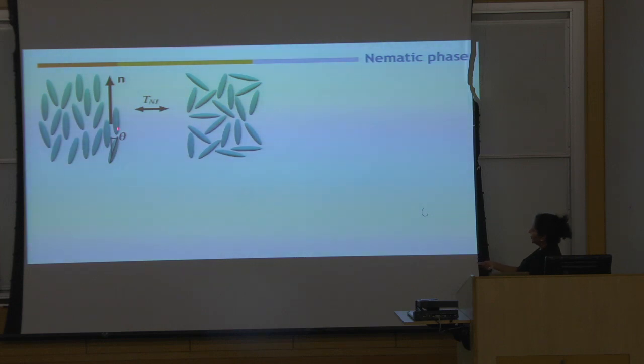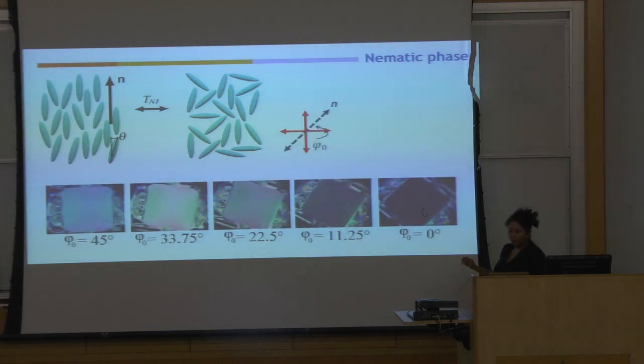The angle between the director axis and the orientation of any particular molecule here is shown here, and this average value gives us a measure of the order parameter. When we are looking at liquid crystalline materials, here's how we view them. We put them under a microscope with crossed polarizers. So we have two polarizers that are crossed. The liquid crystal material is in here. This is the angle between one of the red polarizer axes and the director axis, N. So here, this director axis is oriented this way.